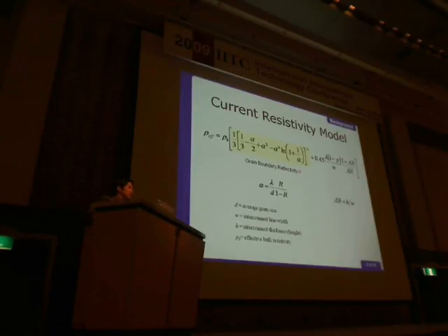I did not. And this is similar to your question. You would obviously expect more interactions with the sidewall, because the sidewall is curving in and the electron wants to go down the conductor. So yes, you would probably see a jump in the interaction between the electron and the sidewall. I would assume that the resistance is then much closer to the minimum line width instead of the average line width, taking the LER into account. So it would be worse. It could be worse, yes.